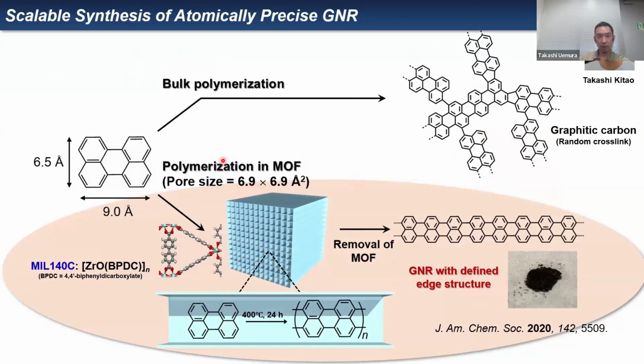But if we use MOFs, we can achieve scalable synthesis of atomically precise GNRs. Actually, when we perform bulk polymerization of this type of monomer, graphitic carbon is obtained with random cross-linked structures. But if we carry out these reactions in this MOF with high thermal stability in the 1D channel structures, we can align this monomer in this way to give the GNR with defined edge structures and with very high yield.